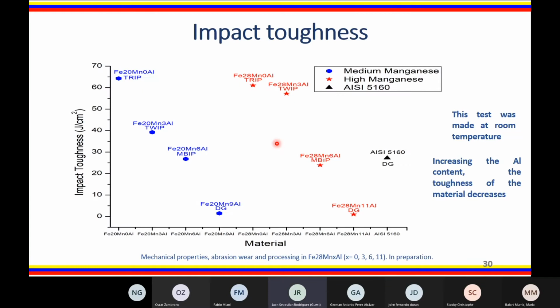On the other hand, we present the effect of aluminum content on impact toughness. It is important to note that the increase in solid solution hardness in FeMnAlC steel affects their impact toughness, causing it to decrease considerably. Increasing the aluminum content, the toughness of the material decreases.